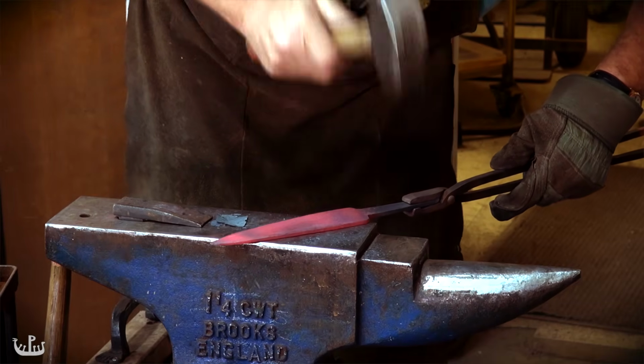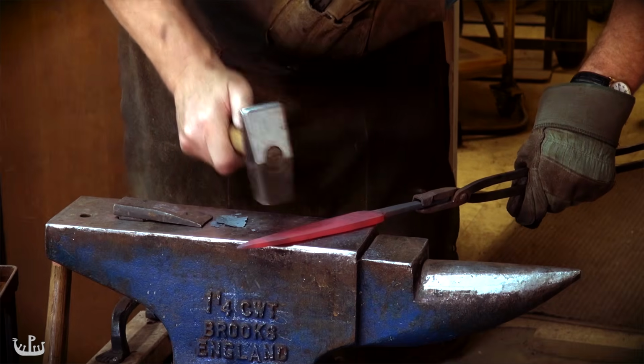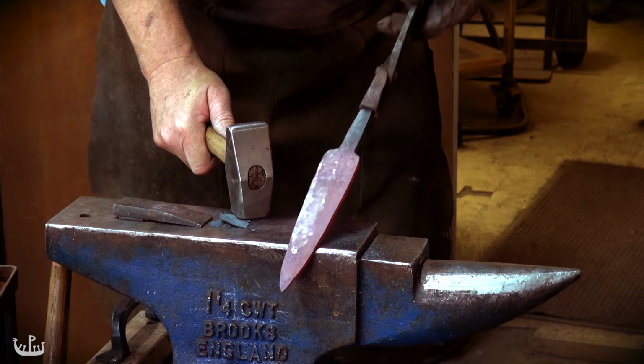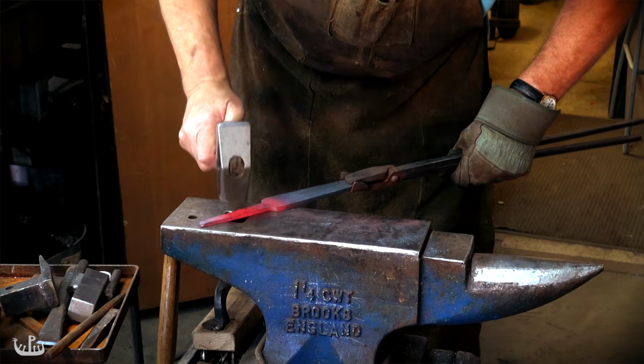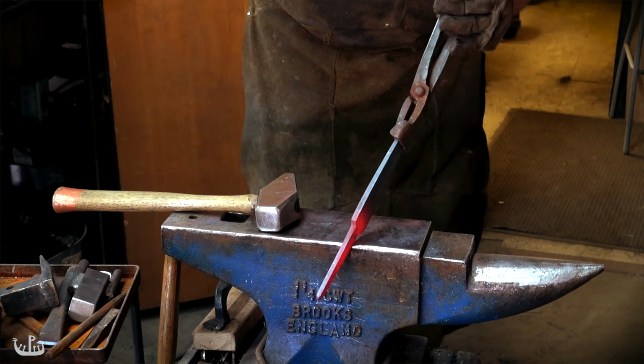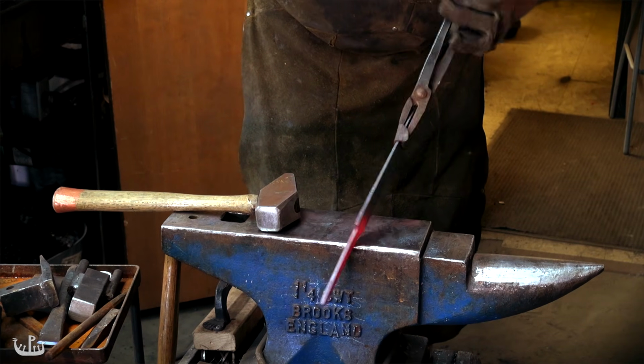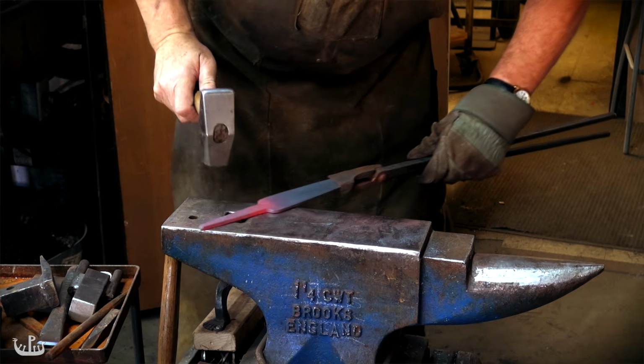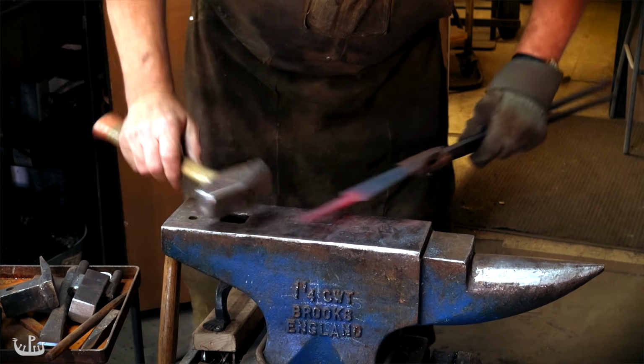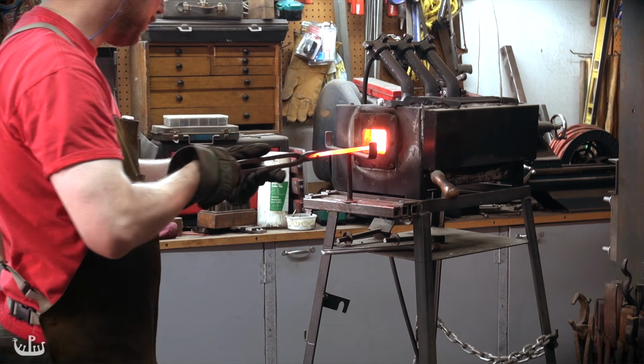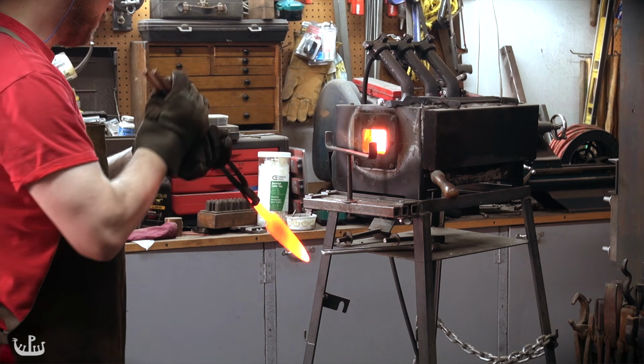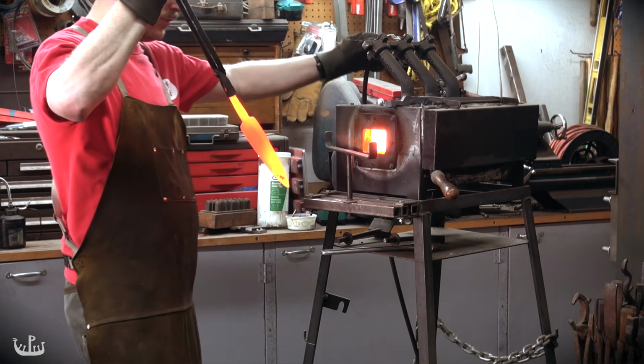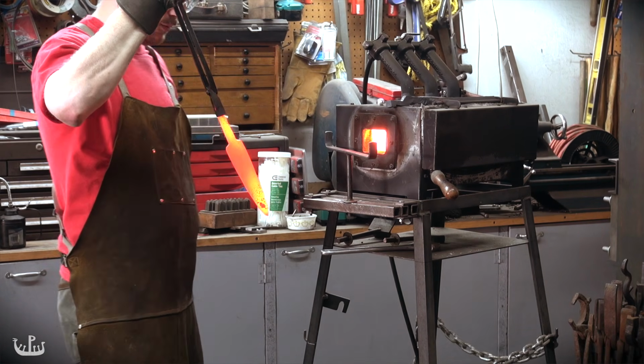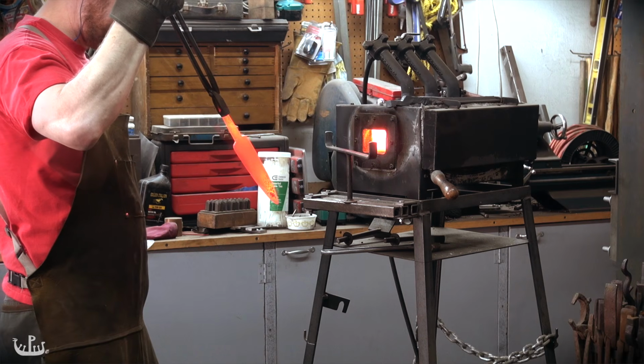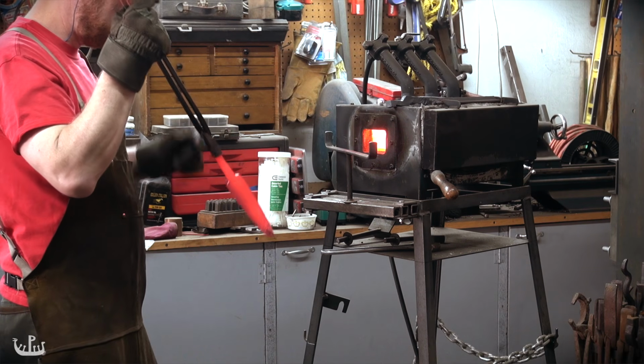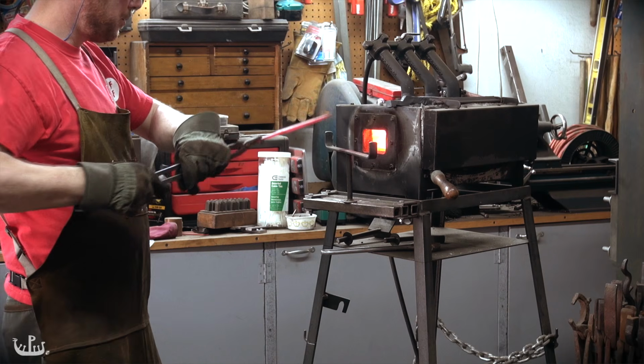In addition to the tapering of the blade width, we also forge in a distal taper in which the back of the blade becomes thinner towards the point. After we are happy with the overall shape, we normalize the blade before cleaning up the profile on the belt sander. The process of normalizing relieves stresses in the blade that build up while forging the steel under the hammer.